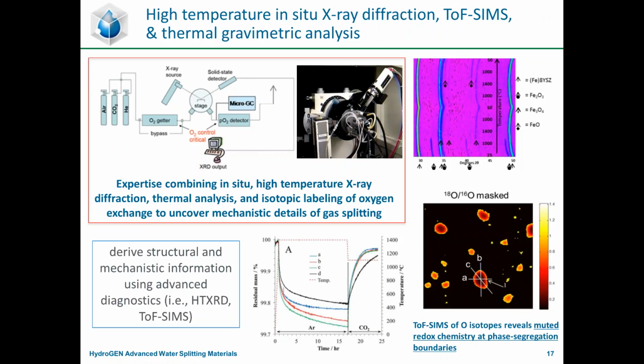This is a high temperature in situ X-ray diffraction technique where an environmental cell can be put into conditions of pressure and temperature that are very similar to, if not identical to, what you'd expect to find on either the oxidation side or the reduction side of this two-step cycle. And you can watch, for instance, the lattice parameter of the material change, and you can actually look to see if phases are coming in and out.